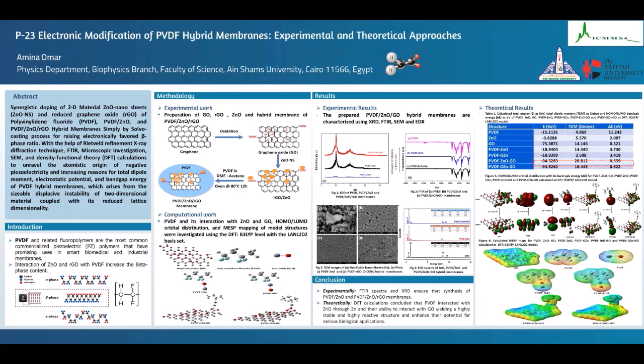From the results of the experimental work, the prepared PVDF hybrid membrane was characterized by XRD, FTIR, scanning electron microscopy, and EDAX. And we confirmed experimentally the presence of the PVDF zinc oxide membrane and the PVDF zinc oxide reduced graphene oxide membrane. And theoretically, from the DFT calculation, we concluded that the PVDF interacted with the zinc oxide through the zinc, and with the ability to interact with graphene, yielding a highly stable and highly reactive structure, which enhances the potential for this hybrid membrane for use in biological applications.